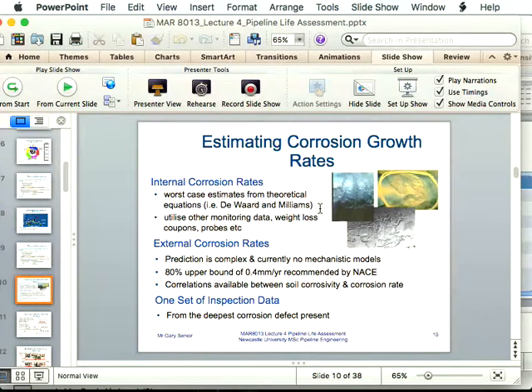They'd be very small, only gram samples, maybe 20 grams, something like that, and they would keep weighing it every 3 months, whatever. Then they'd get a predicted corrosion rate for that material, and they would correlate the corrosion rate of the coupon and try to translate that to the rate at which the pipeline would be corroding. This would be internal corrosion, fairly obviously, because it's induced by the product, as opposed to external corrosion, which is a result of resistivity between the pipeline ground and the pipeline external surface, and water content there, as well as a galvanic cell that would generate it. But that's on internal corrosion.